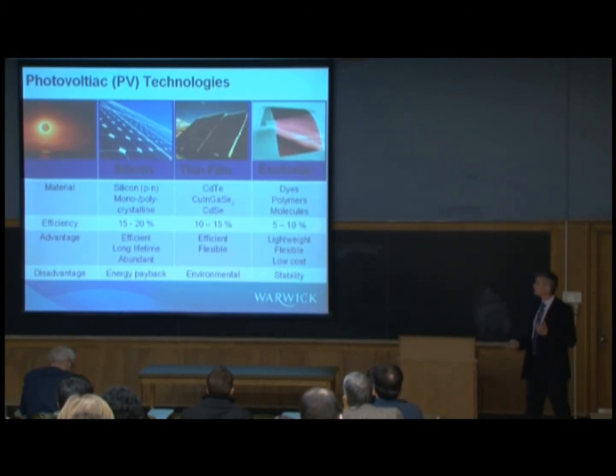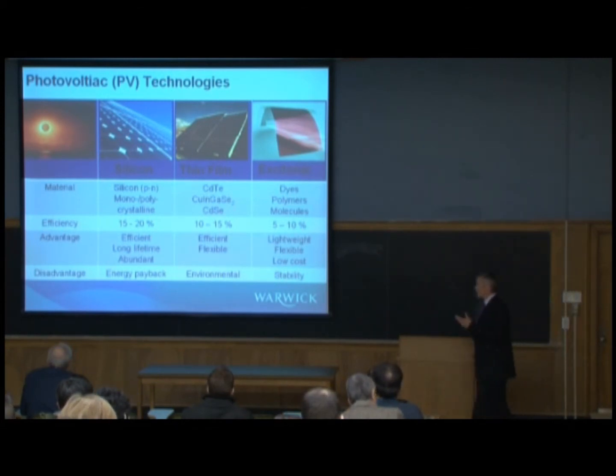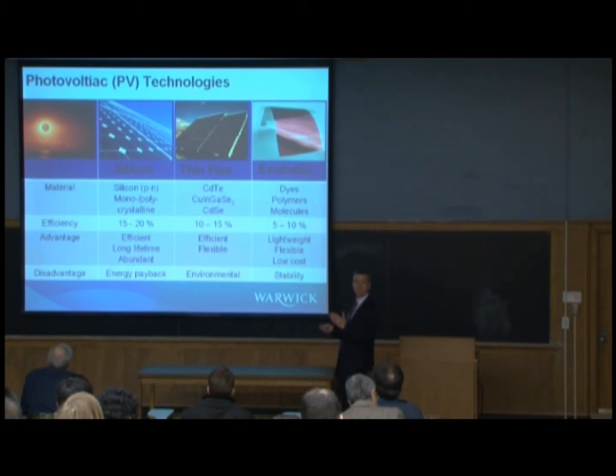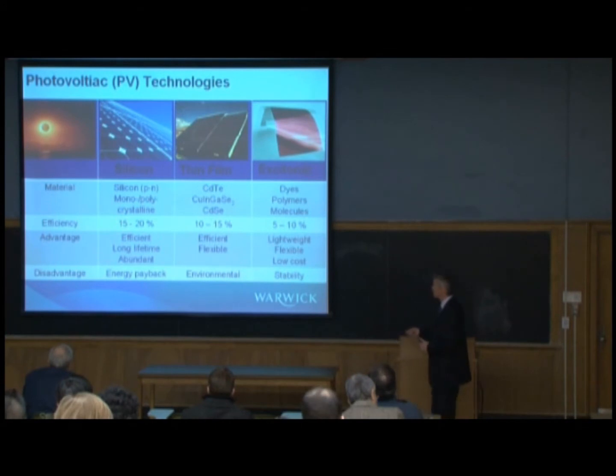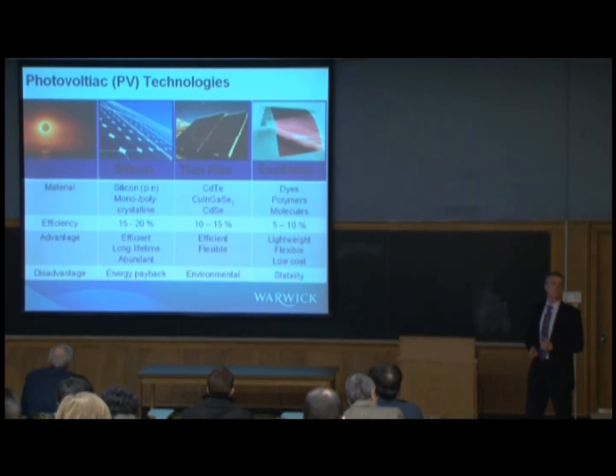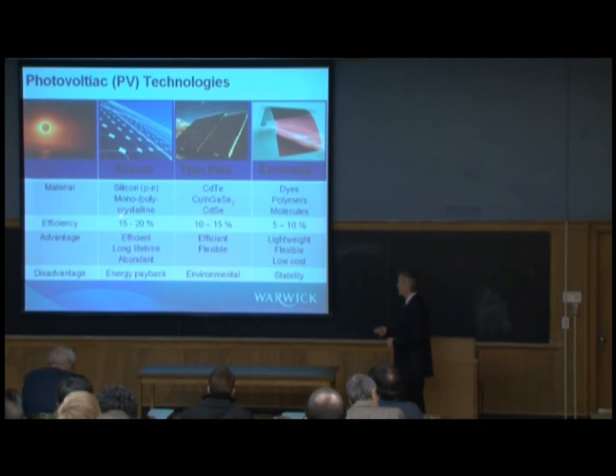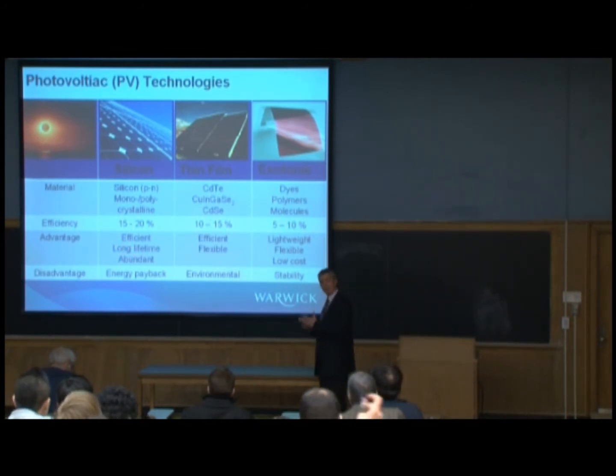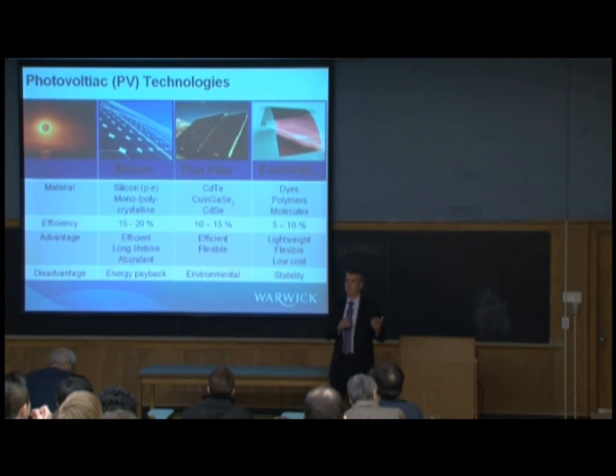First generation cells, here based on silicon. Polycrystalline, multicrystalline silicon, the PN junction, been developed for a long time, pretty successful. In fact, the efficiencies are 20 to 25% nowadays. Modules are 15 to 20%. They work very well. Long lifetime. If you buy a solar panel and put it on your roof, it's guaranteed for 25 years.